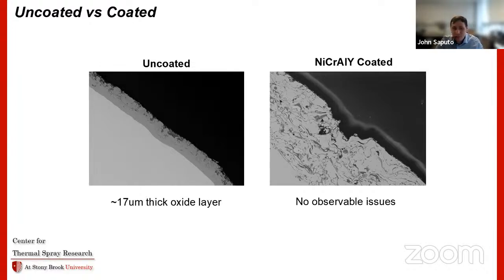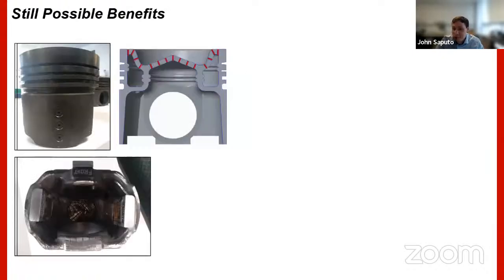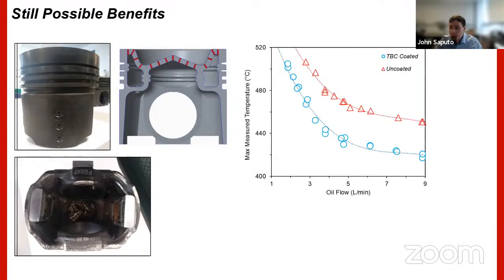So this really enables you to go to these higher temperatures in these systems and not have too many issues. So there are still other benefits that are possible to gain out of this. Again, going back to these telemetry pistons, you can put a thermal barrier coating on top of these things now and look at how the temperature actually reduces in these systems. So the blue curve in this is a TBC coated piston, and the red curve in this is an uncoated piston. And you see a couple of interesting things.